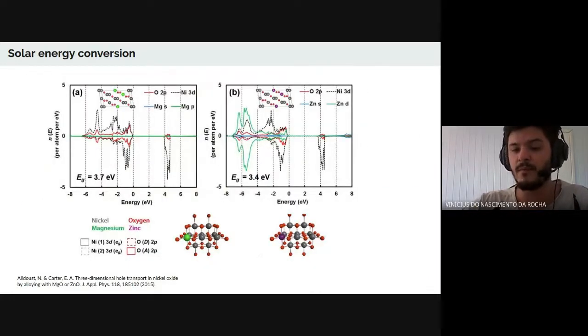Alloying instead with magnesium oxide or zinc oxide transforms nickel oxide from a 2D into a 3D conductor by reducing interplane hole transfer barriers, making it an intriguing candidate for a transparent conducting oxide in photovoltaics. Alloying nickel oxide with magnesium oxide and zinc oxide retains the large band gap of nickel oxide and hence its optical transparency while improving its conductivity. Because nickel, magnesium, and zinc are all inexpensive elements, this material could replace, for example, conventional transparent conducting oxides in photovoltaics that contain the rare and therefore expensive element indium.